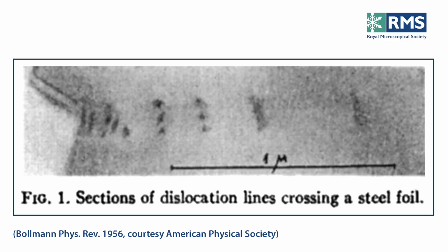Well, I'm going to show you in a minute a film in which you can see the moving dislocations. But before I do this, I want to show you another slide, because around about that time, a little bit later, but not much later than our publication, there was a publication by Bollmann in Zurich, Switzerland, of these spotty lines, which you can see on this picture, which were interpreted as dislocation lines crossing inclined to the plane of the foil, and the material he was using was in fact stainless steel. And in a minute, I want to just ask you why they're not lines, because they appear to be dotted.